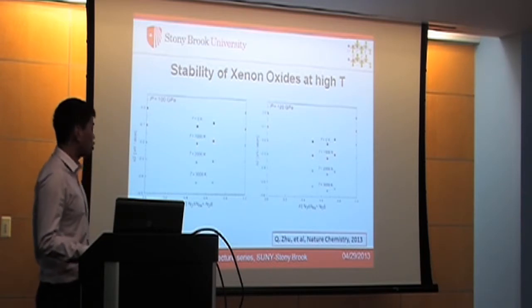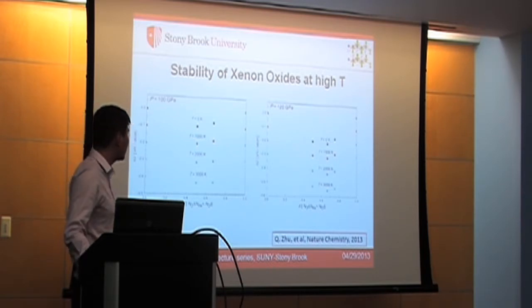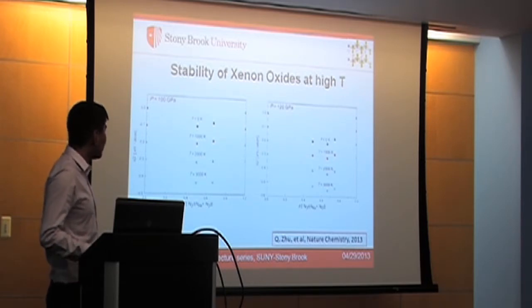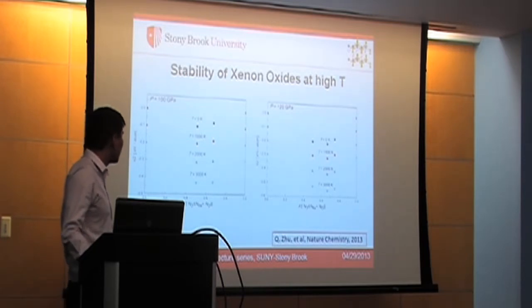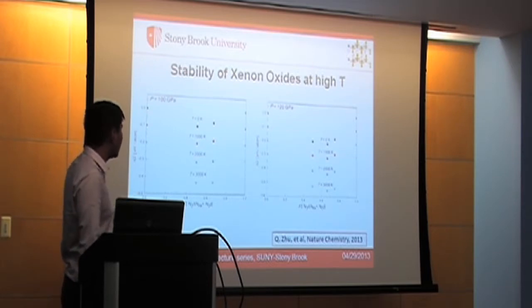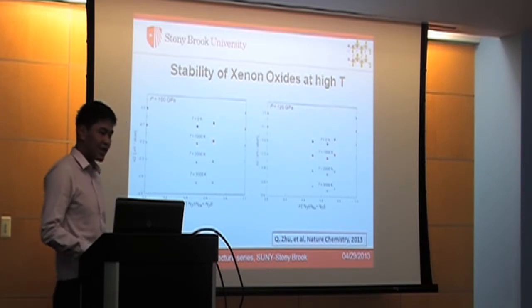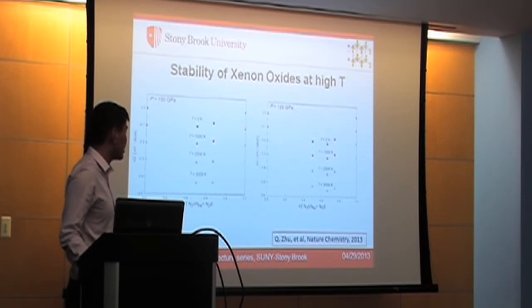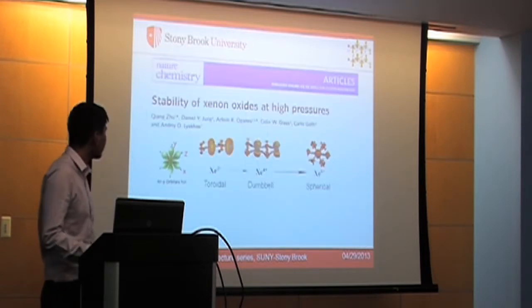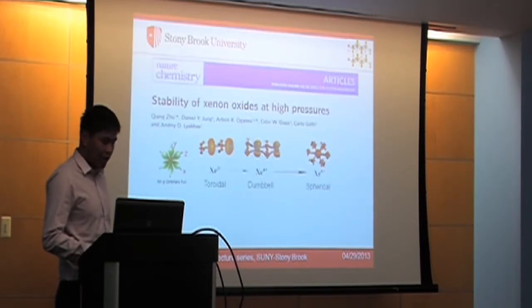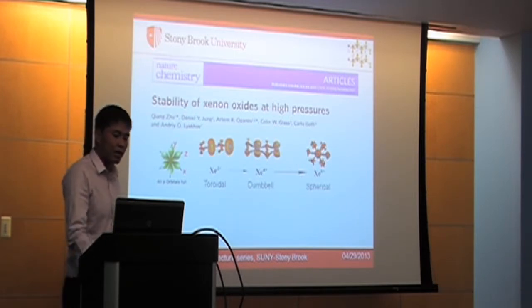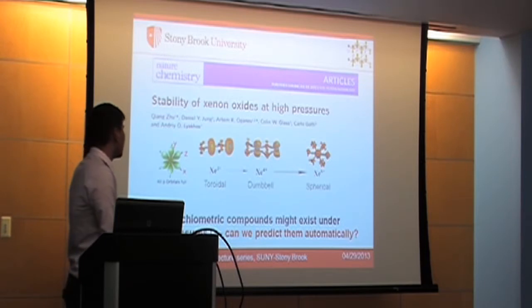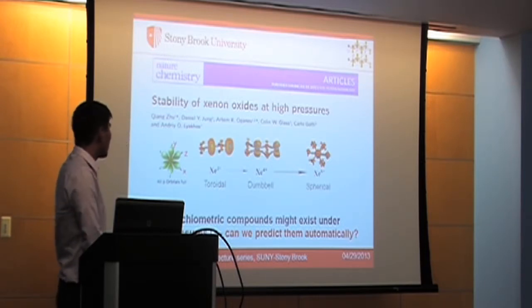We did this by a so-called quasi-harmonic approximation method, and we studied the effects introduced by the temperature, and we found that when we increase the temperature, the shape of the convex hull doesn't change at all. So it means that the thermal effects do not qualitatively change the stability of those xenon oxide structures. So we can propose the stability of xenon oxides at high pressure. And this example also shows us an important rule: new stoichiometry compounds might exist under high pressures.